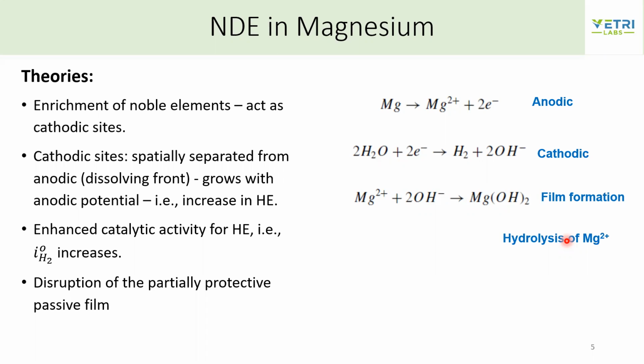Another important factor that people consider is the protective passive film present on magnesium, which is very weak—partially protective or very unstable. And when this passive film disintegrates, you have a highly active surface that gets exposed to the environment, and so the NDE occurs.